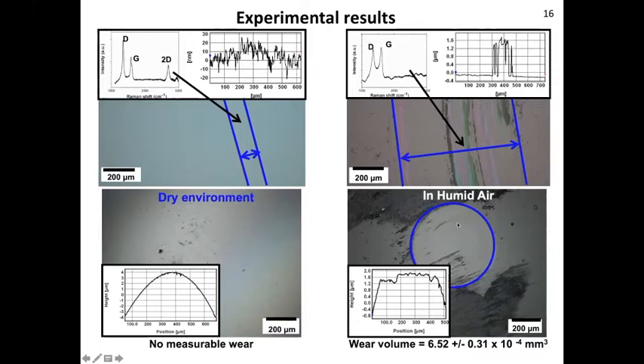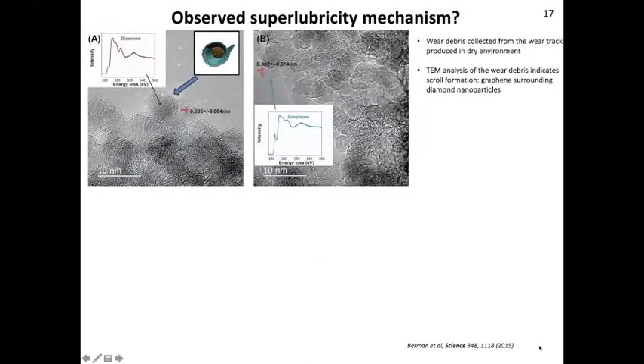And then in contrast, in the case of the humid environment, we've seen a pretty decent change in the wear. We actually observed lots of material transfer from the ball side to the flat, and then we see this huge wear scar on the ball side. So the bottom one is the ball in both cases. In this case, we couldn't really measure the wear. Here, the wear volume was pretty large and consistent.